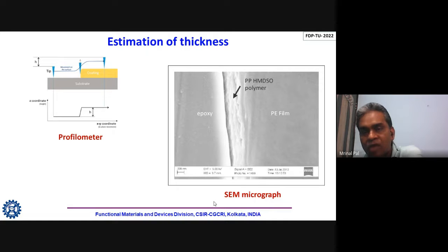As long as you are on the film, it will be the same contrast. When you are coming to the interface, in between your thin film material and the substrate, there will be a kind of interface, and in that place there will be mingling of your substrate material and also your film material. That's why this is high contrast, okay? And once that is covered, then you come to your epoxy region, which is again of uniform contrast of a different type. So from here also, you can directly measure the thickness of your film, this PE film, this one is your film thickness, and the one in the middle, which is more bright, will be the thickness of your interface, and then the substrate.